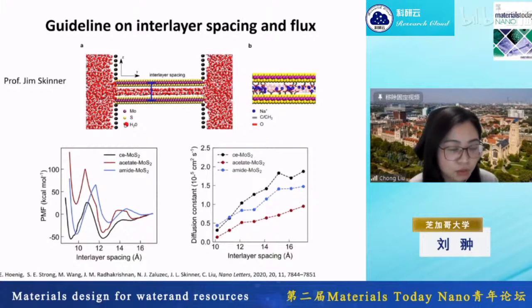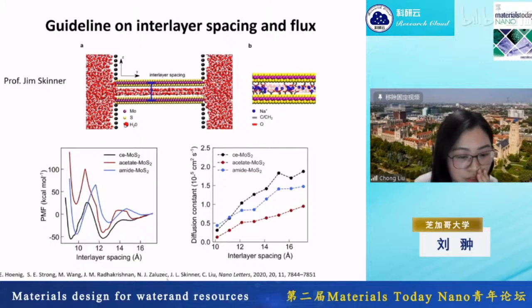So actually, whenever you have already determined what kind of functional group you want to put into this channel, your channel width is determined because the molecules you put in there have an affinity to water. And it's not the molecule size that's determining the wetting state interlayer spacing. It's the interaction between the molecule and water that will determine whether you would prefer one layer of water in this channel, two layers of water, or three layers of water. So you have these discrete energy wells, and for each different molecule, your global energy minimum is at a different place. Some membranes would prefer two layers of water, and some of them would prefer one layer.